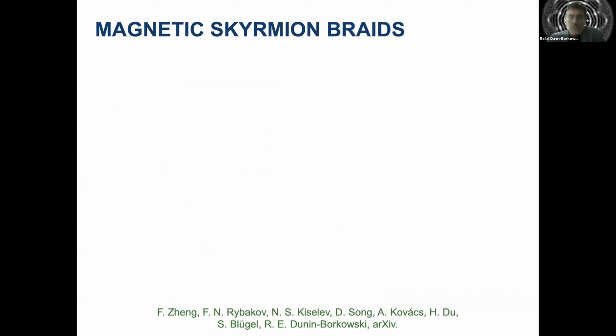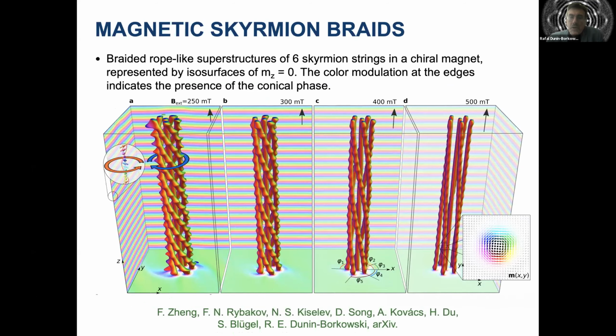And more recently, our colleagues predicted theoretically that if some magnetic skyrmions assemble together in a small close-packed arrangement, then at certain values of applied field, they don't form straight strings, which are seen on the right, but at lower values of applied field, they start to twist around each other to form what are termed braided rope-like superstructures. And these have also never been observed before experimentally, to the best of our knowledge.